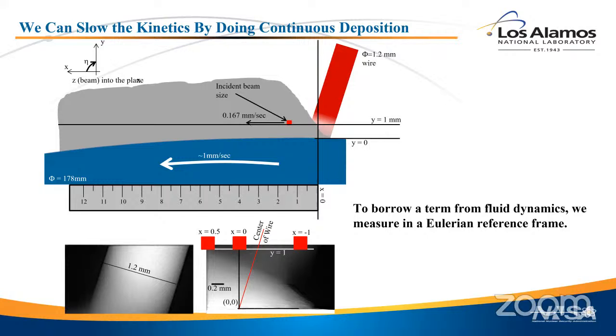Because you're continuously putting heat in, that greatly slows down the cooling rate. But what it also does is set up a quasi-steady static situation at the point where the melt pool is, right? Because as you're depositing material and it's solidifying, it's being moved away by the rotating wheel that you're depositing it on. So after the first amount of time that's transient, you set up a quasi-steady state. And that's true as long as you're integrating at a long time relative to the wire motion, which we are. So we're actually going to integrate for a second on here.